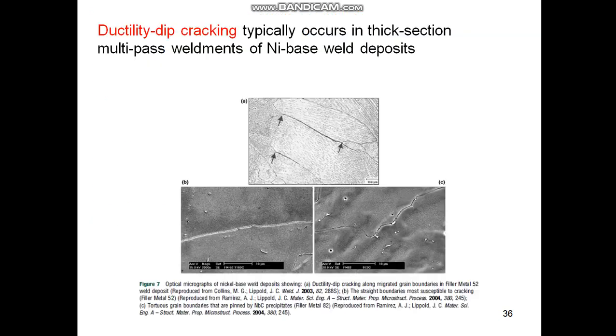Above is the optical microscopy image of the weld deposits, and below is a more magnified image. You would see it is welded with filler 52, and you will literally see a crack and also the presence of some intermetallics on either side of the grain boundary, right? So this happens most of the time in thick section multipass welding, ductility dip cracking. This is again a capture from Lippold, a popular book on weldability of nickel based alloy. I recommend the viewer read the book in detail for understanding the mechanism.